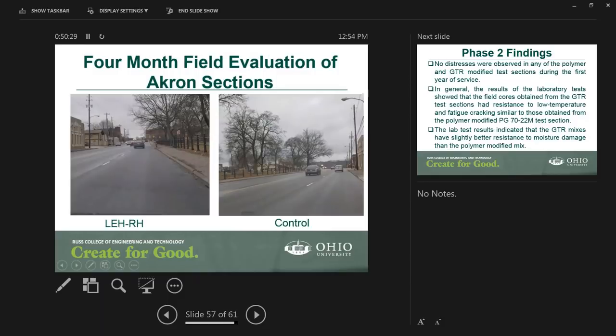So the latest evaluation was done last Friday. So we got those pictures in the rain. Again, based on that evaluation, we did not really see any difference. We did an in-depth evaluation back at the end of December, and basically there were no differences in terms of performance. Both sections had a good performance with no issues reported so far.